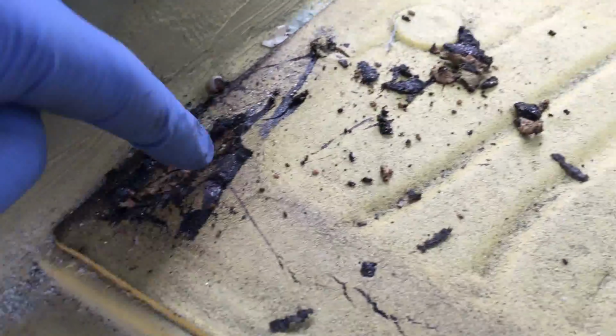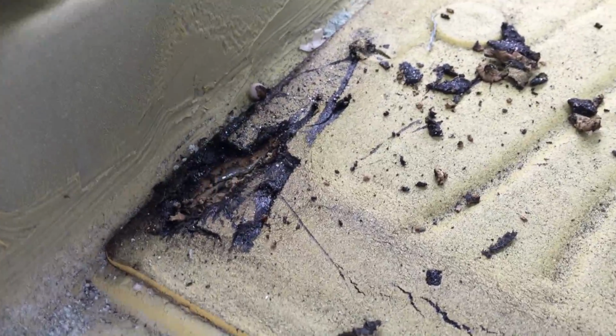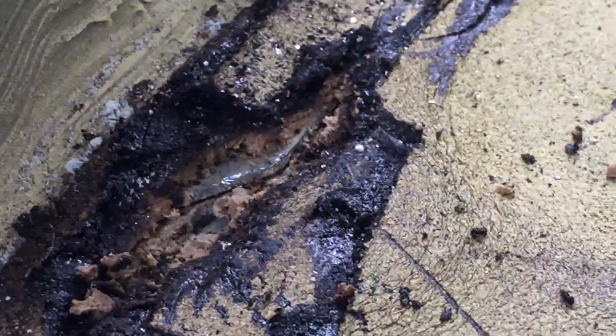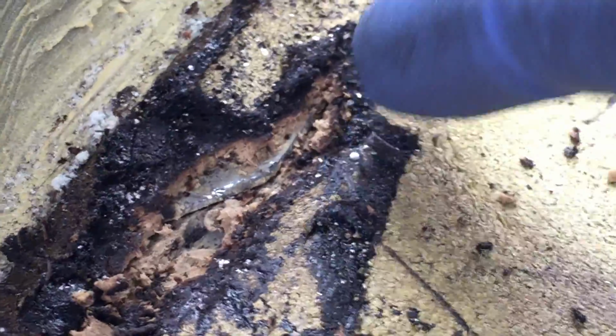We can also see possibly the owner or previous owner has been having a look, see if the floor's moved here. This is how we found it. So there's a very slight gap, not much at all, but maybe 1 to 2 millimeters, just where the rear axle carrier panel's just started to drop very slightly away from this piece, which is the chassis leg. So it would be a great time to stitch weld this as well, and just relieve the sheet metal work of relying on spot welds to hold everything together.